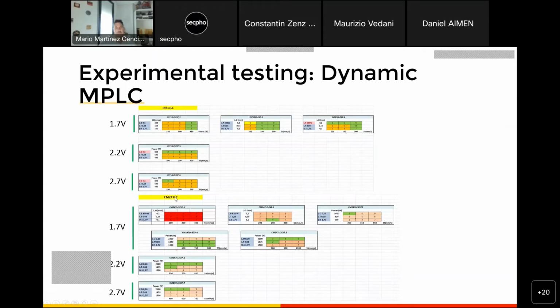Meanwhile, in the CM247 low carbon, we played with just the opposite. So very high power. The limit of this optic is about 2 kilowatts. So we played with very high power, but again, on very, very high scanning speed. And that's because we wanted to map what is happening in different ranges. We have a limited time and we have two materials to produce, and so our idea was to go on with different approaches depending on the material. So all in all, you can see here that the green squares mean that we got samples from these conditions, whereas the orange samples highlighted mean that this coupon had to be stopped during the process because of building issues, right?